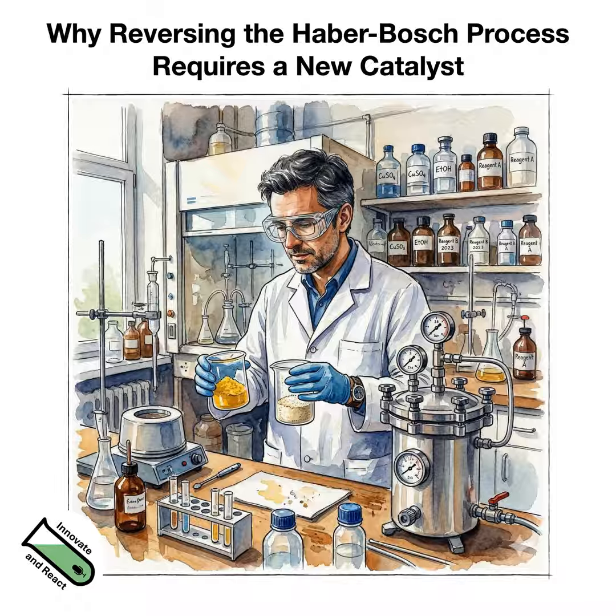Because the metal sites are blocked, or? Well, the metal sites are still there. It's still active. An iron nitride would still expose iron atoms at the surface. But I think in simple terms, you can think of the iron as already surrounded to some extent by nitrogen in its bulk. So it's maybe less prone to adsorb nitrogen from the atmosphere. Iron is already in a happier state than if there was less nitrogen around it, and that lack of metal-nitrogen binding of a nitride compared to metal is detrimental for the catalytic turnover.